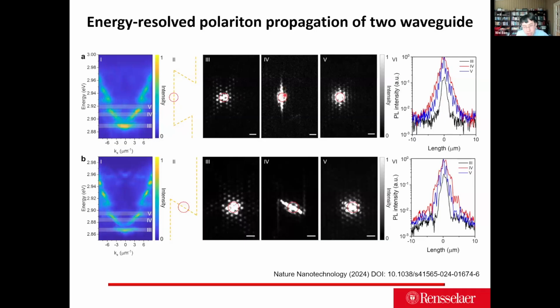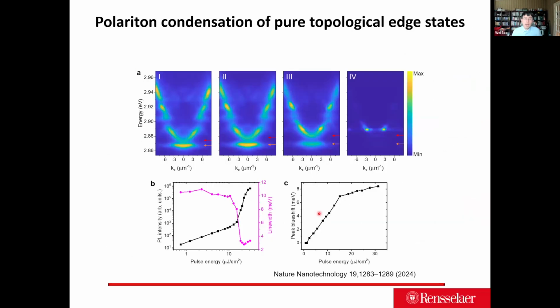So we see a combination of some of the bulk modes, and then the topological edge states propagate. So that matches the experimental simulation. The experiment and simulation match each other. By pumping this topological edge region into polariton condensation, you can see the condensate, with the right detuning, can condense inside the band gap of the topological gap.